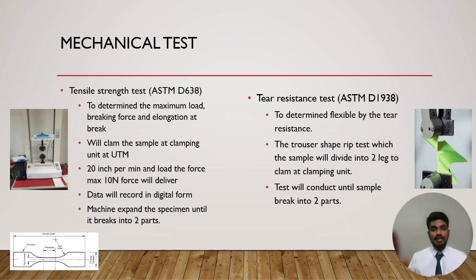So the tear resistance test will be done according to ASTM D1938 to determine the flexibility by the tear resistance. The trouser shape test, in which the sample will be divided into two legs, is clamped at the clamping unit of the universal testing machine. This test will also be conducted until the sample breaks into two parts.